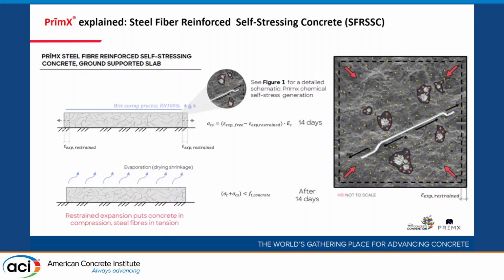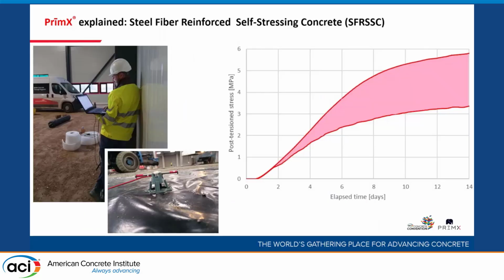So we use a relatively high dosage for the industry standard, premium quality, high tensile strength steel fibers to restrain the expansion and put concrete in pre-compression. So that's the backbone of self-stressing steel fiber reinforced concrete works. So we also monitor the expansion on site with different types of sensors, and then through the mathematical approach we have developed, you can actually recalculate the in situ expansion, taking into account the restraint and other properties into the pre-stress you are generating with this system during the curing.